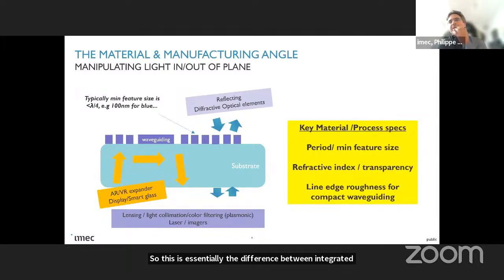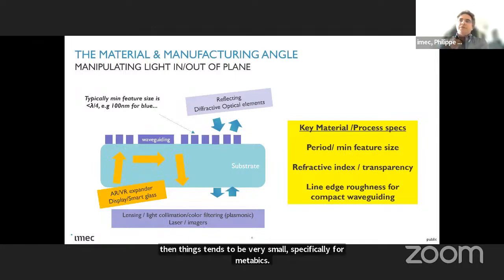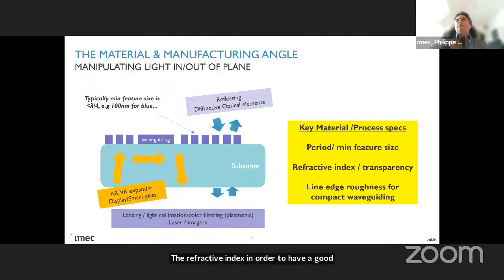And there are for us critical aspects in terms of coatings and thin films. First is the feature size. Obviously, when you want to manipulate the light towards the lowest wavelengths, then things tend to be very small, specifically for meta-optics. For the refractive index, in order to have a good core, the transparency is important. So at which point do you decide that you have a waveguide or not? It's actually a perpetual debate in the organization, believe me. But essentially, that's what it comes down to, the transparency. And what we do care about as well, which is somehow related, is the line edge roughness or eventually the surface roughness of the coating that we are using.